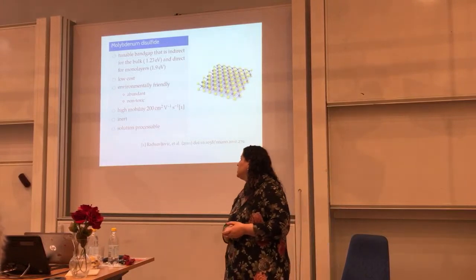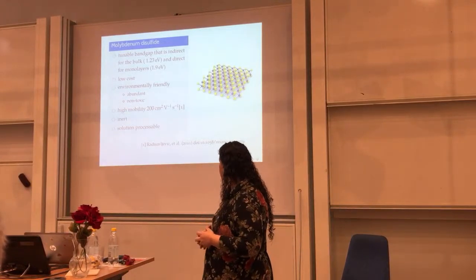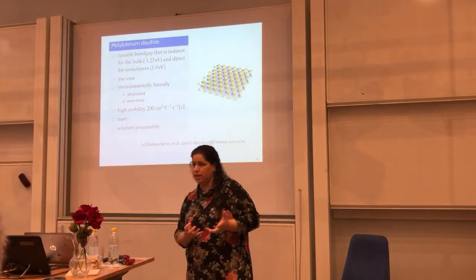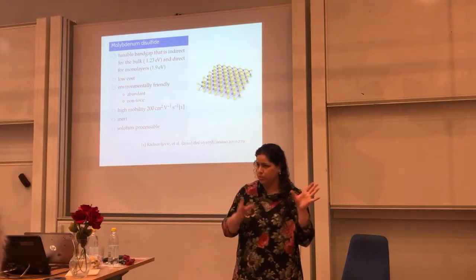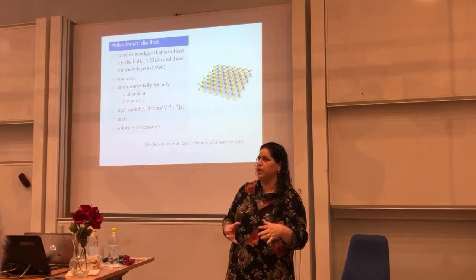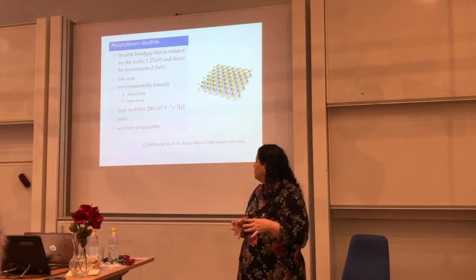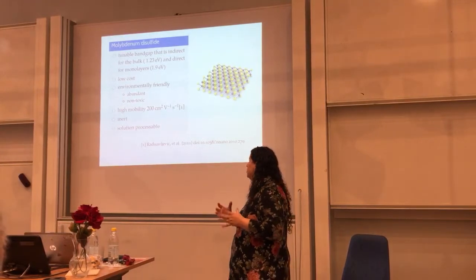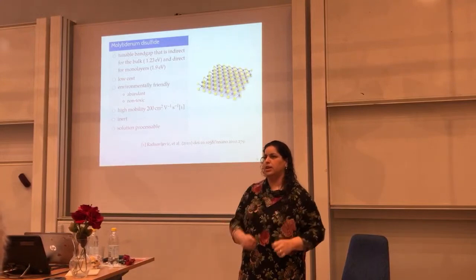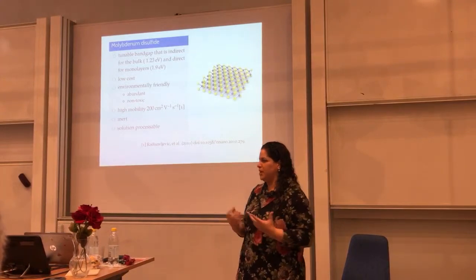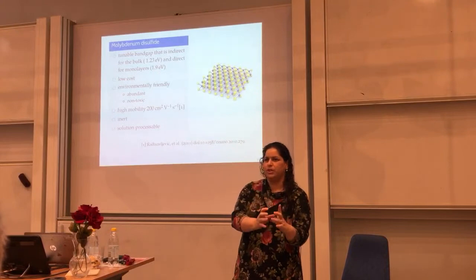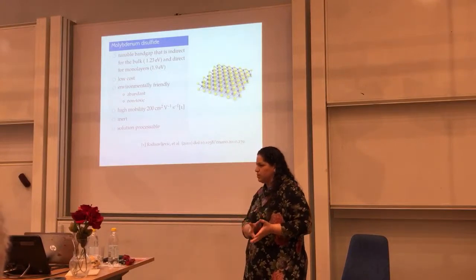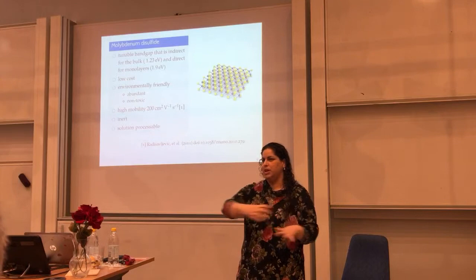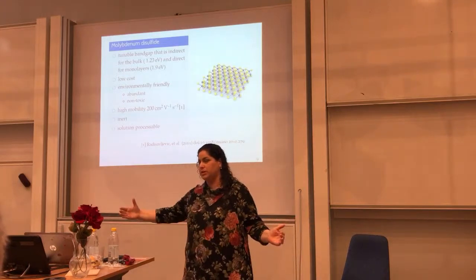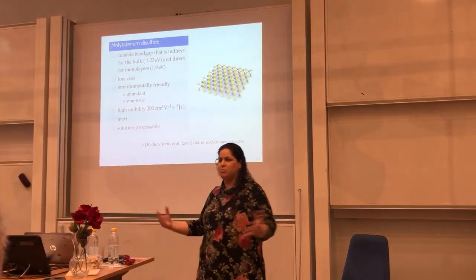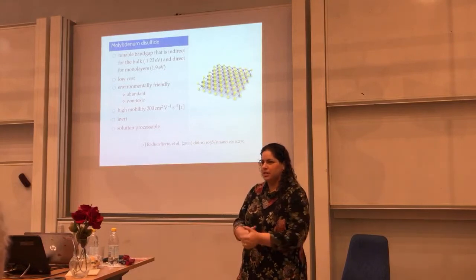And initially, his view was that if we have a flake, like Magnus Humegard built a device to measure mobility in the lab, and then we measured the mobility that was 50 square centimeters per volt second in one tiny flake. And that was just so great. So imagine if you can have one flake with 50 square centimeters per volt second in mobility, and if you put many of these flakes in a square kilometer area, you can make solar cells on paper. So that was the idea.